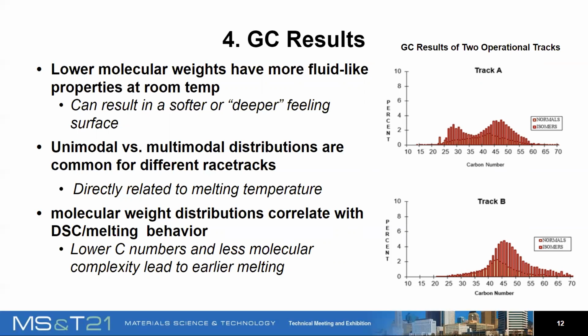In general, lower carbon numbers and less complex molecular structures lead to the wax melting at lower temperatures, as these molecular structures require lower energies to separate or degrade, essentially. It is also important to note that the test cannot identify the isomer content and must be done with a TGA.